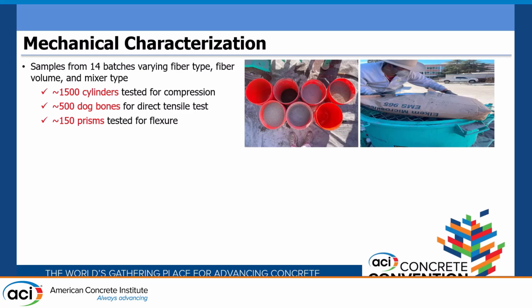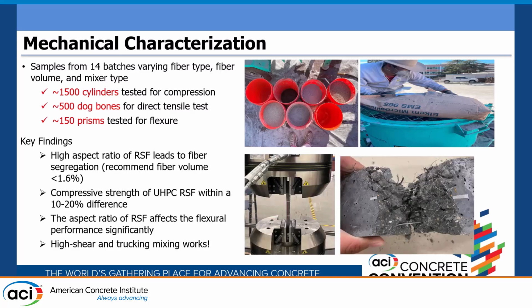I developed around 1,500 cylinders that I tested in compression, around 500 dog bones for tensile tests, and around 150 prisms for flexural testing. The key findings: high aspect ratio is going to have a lot of problems in terms of fiber mixing. We see a lot of segregation, so we have to limit the fiber volume to 1.6%. But if you use a low aspect ratio, with shorter fibers, you can go to more than 6%.